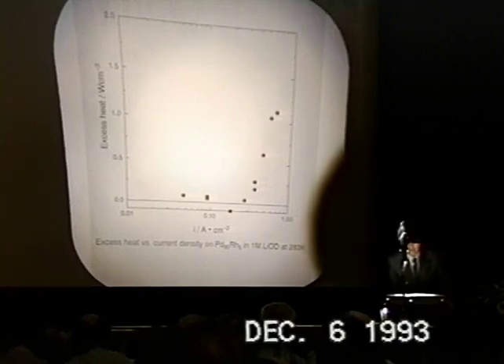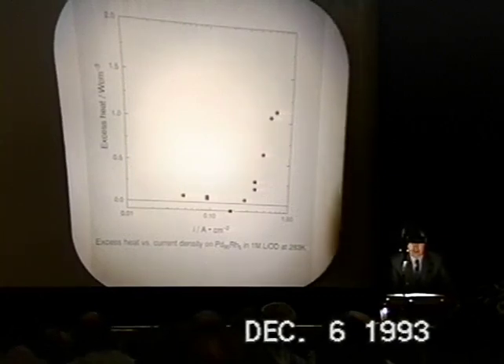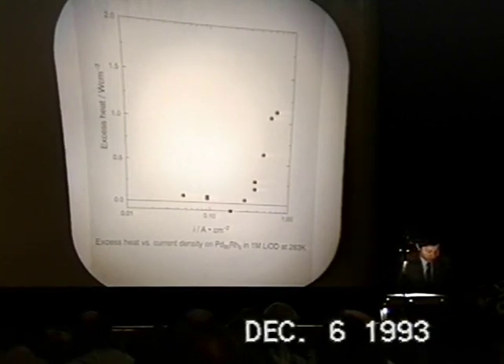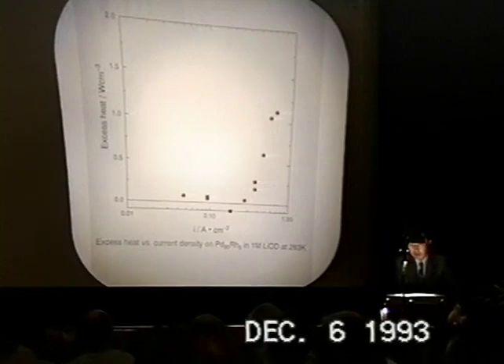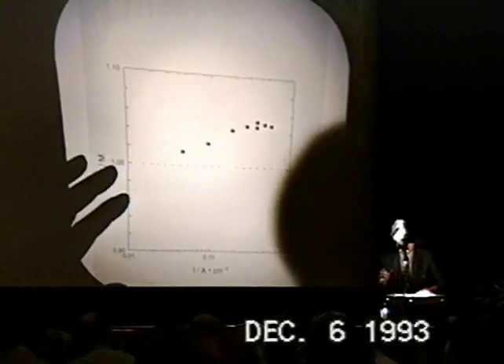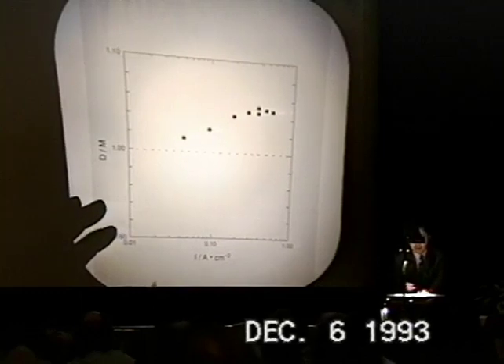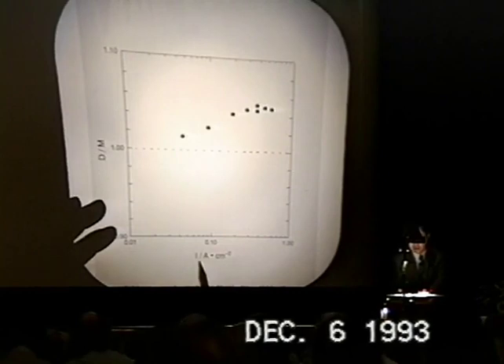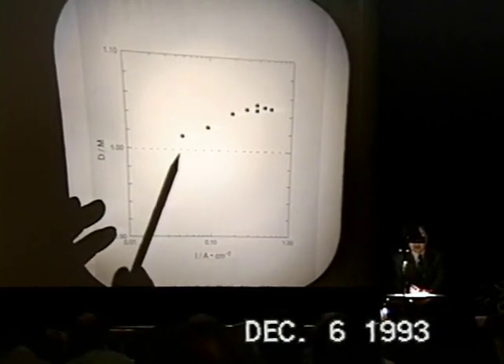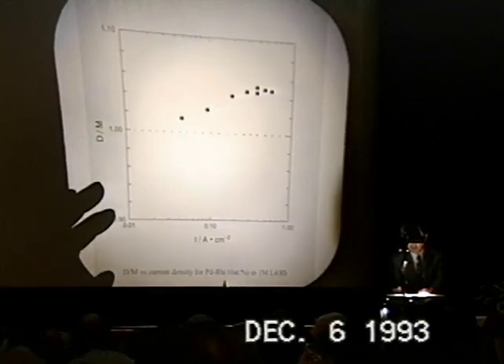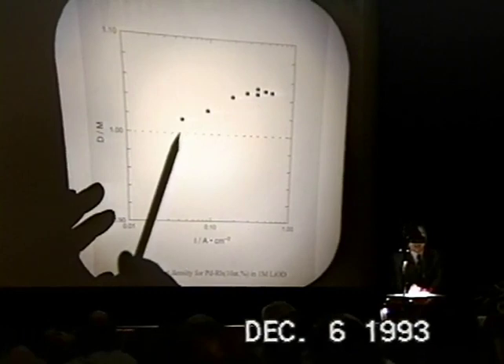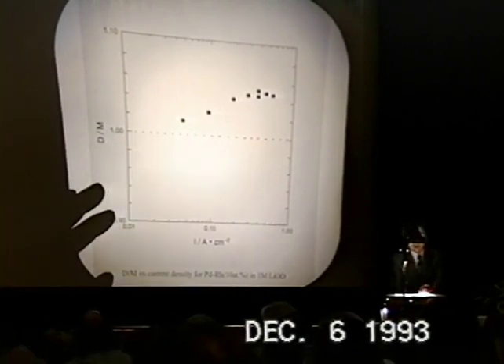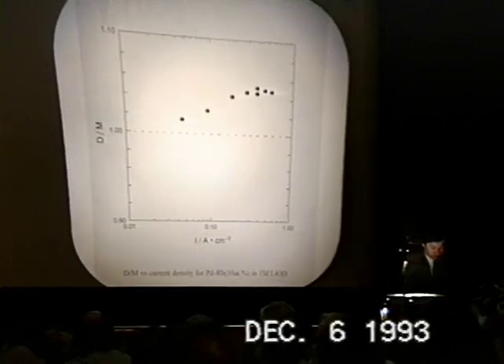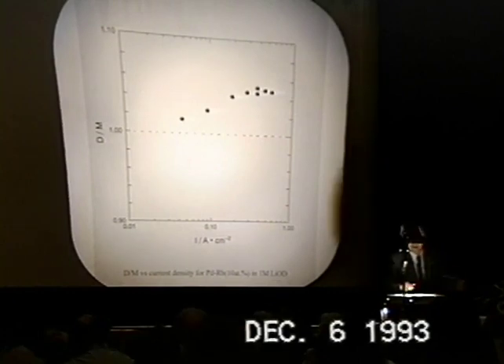So we thought maybe we should try 10% rhodium palladium alloys. With 10% rhodium palladium alloys, we have this. I'm not showing the actual data to show the time dependence, but I'm showing D over M as a function of current density. So you can see clearly that D over M on this 10% rhodium palladium alloy shows loading ratio higher than 1.0 nearly all the time. But we have this at the moment.